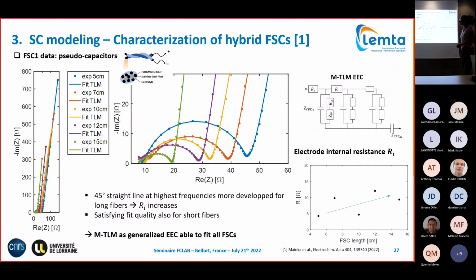For the next slide, I skipped the fitting curves obtained with the Randles circuit and just use the modified TLM. Here you see the dots, the experimental data measured for our fibers with varying lengths, between 5 centimeters in blue and up to 15 centimeters in green. With increasing fiber length, the 45 degree slope at the highest frequencies is more pronounced, which is logical for long, thick electrodes. As I reminded you, the 45 degree slope is associated with charge transport along the electrode length, so volumetric character. And for very short fibers, we have an almost perfect semi-circle corresponding to a Randles type circuit, meaning an interfacial electrode.